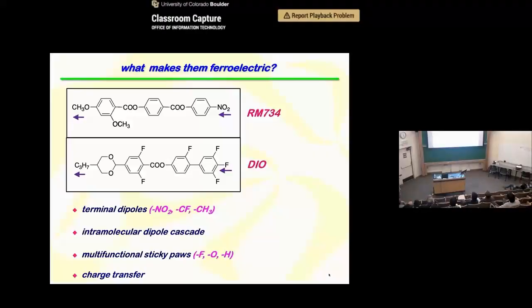We have 7 H's. This end group is very flexible, so it can bend around to get into interactions with this end of a neighboring molecule. And we have the same situation here, 3 H's and 2 oxygens. In general, the dipoles and no contravailing dipoles give you some net charge transfer from one end of the molecule to the other. So this end is negatively charged and this end is positively charged. So you have some direct charge interactions in an end-to-end assembly.